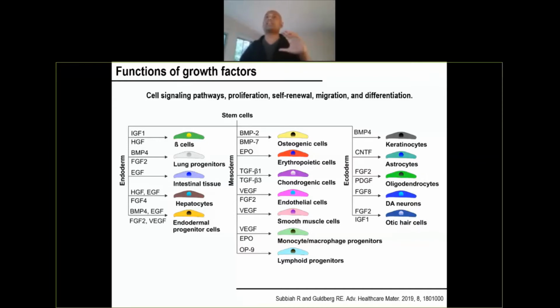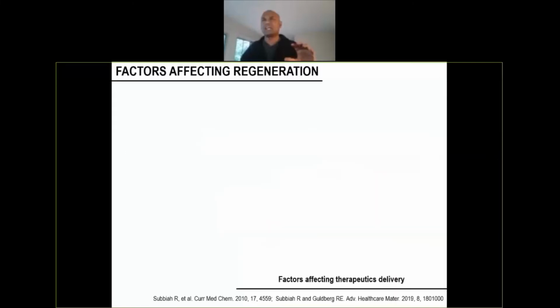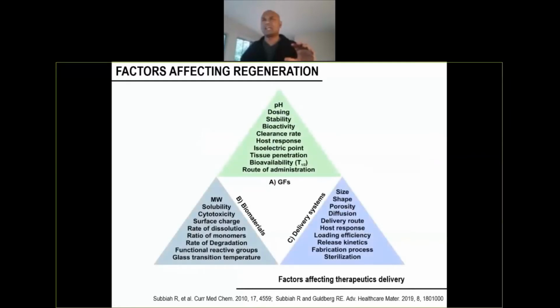And that can be controlled by the concentration of the cross-linker that you use. The beauty of this cross-linker is that you have native, freshly derived cellular matrices, ECM from the cells, and then you add 0.1%, 0.5%, 1%, 2% of genipin to cross-link. What happens? The structure remains the same, the protein remains the same, but the mechanical property increases upon cross-linking, from 100 Pascal to 20 kilopascal. The graph shows here from 100 Pascal to 10 kilopascal, when the concentration is kept between 0 and 2% weight by volume of the cross-linking agent. Then this biochemical cue is very, very tunable. When we say tunable, that means you can control the stiffness of the extracellular matrices.